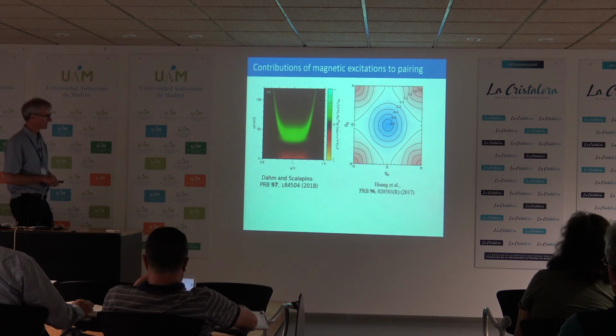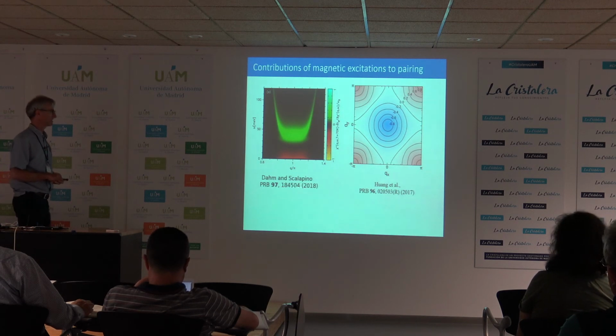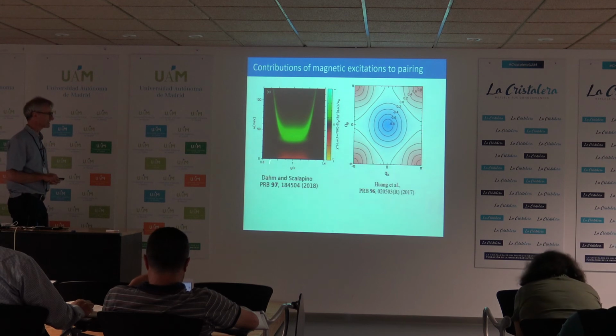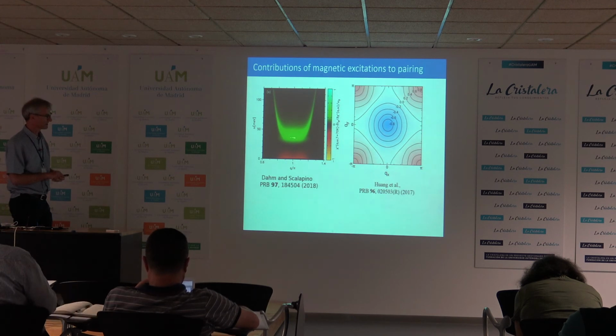And here we have another calculation on YBCO based on Bernhard's data, where they've worked out which of the excitations, now in the superconducting state, contribute to the pairing. You can see the green ones here, the high energy mode above this peak feature, contribute mostly to the pairing. The low energy excitations, even though they're at pi, actually contribute against the pairing.